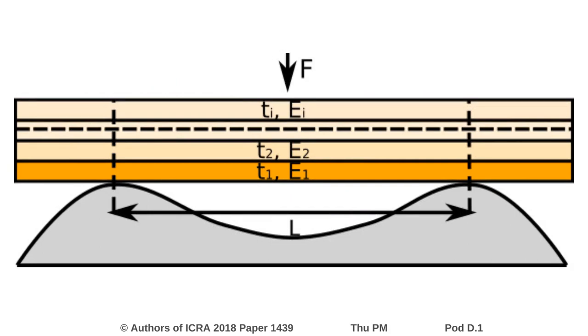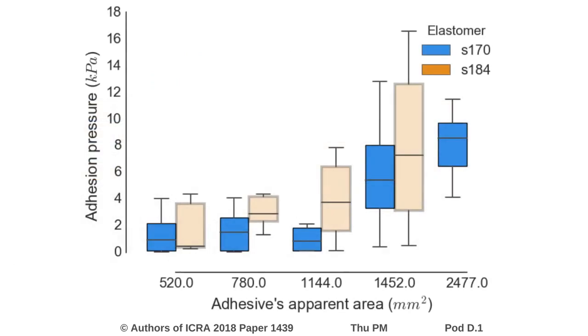Previous work on flat films demonstrated that for equivalent contact area, shear adhesion strength is proportional to the inverse square root of the shear compliance of the adhesive. Experiments between hybrid adhesives of similar bending compliance and varying shear compliance demonstrated that holding contact area constant and increasing shear stiffness increases shear adhesion capacity.